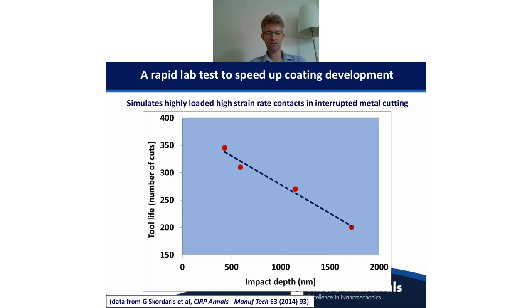So say the other key application area for the impact test is in simulating metal cutting applications. So here's an example from the literature from one of our customers a few years ago. And what they've shown here is a very clear correlation between the number of cuts until the tool failed and the performance in the nano impact test. So essentially, when there's a very high depth at the end of the impact test, that's because the coating has fractured, and this is again correlating to a large degree of coating fracture in the actual test, which is leading to a very limited amount of tool life before it fails. And conversely, you can get a lot more life out of the material that doesn't fracture in the impact test.